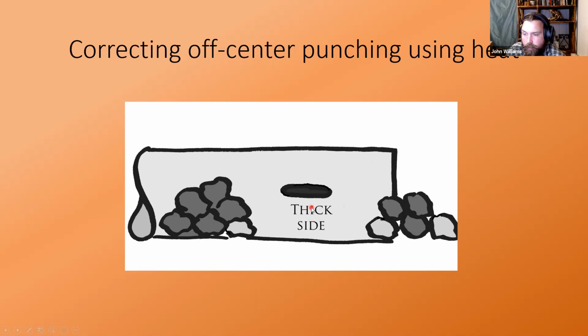The other way that you can mitigate that a little bit is you can have a watering can, and in addition to heating the thick side, you can also cool the thin side. And to do that, the best way is to put the edge of your punch a little bit off parallel with the ground, so that the water will run off of it if you pour on that inside edge, and you pour it right down the inside edge so that it spills out only on the thin side, cooling that side.